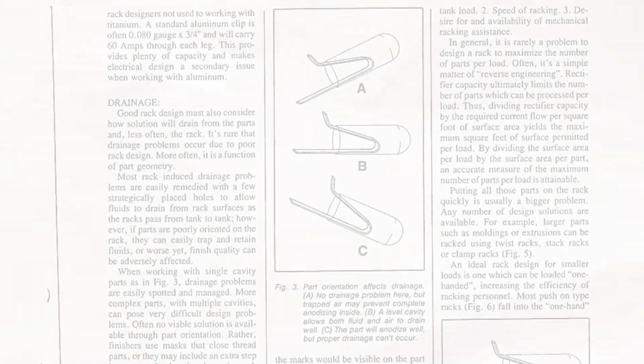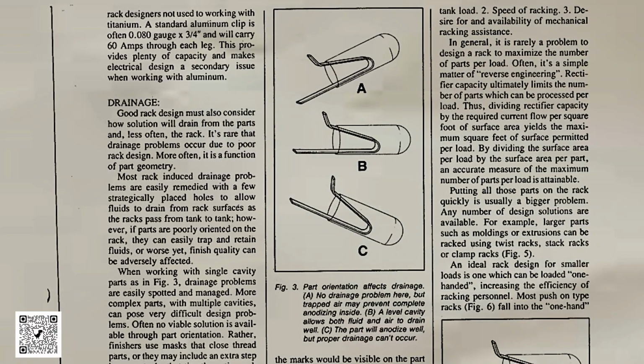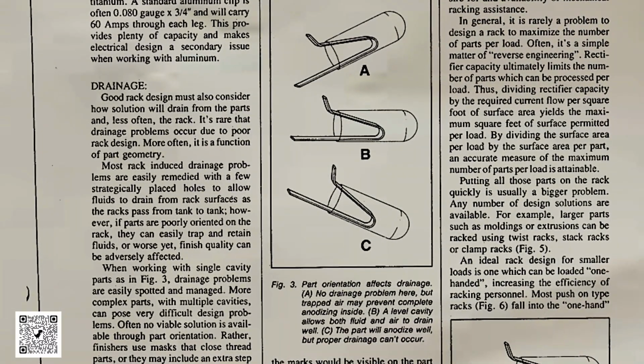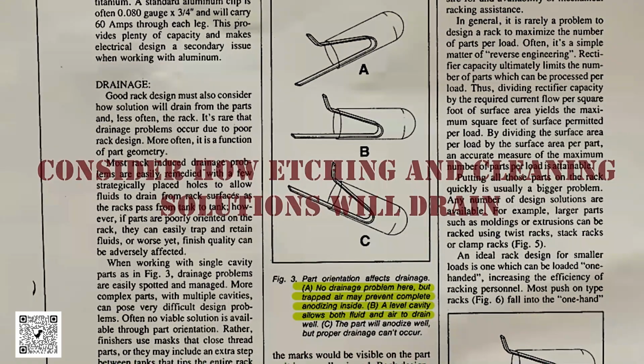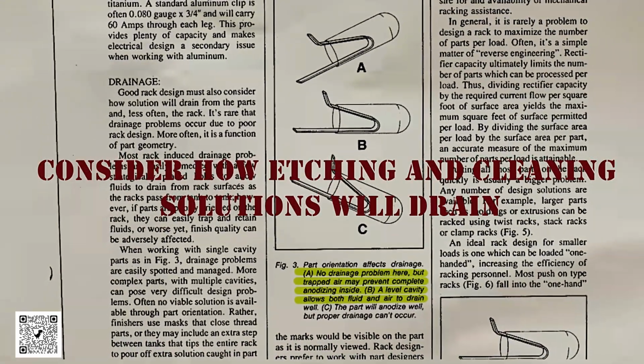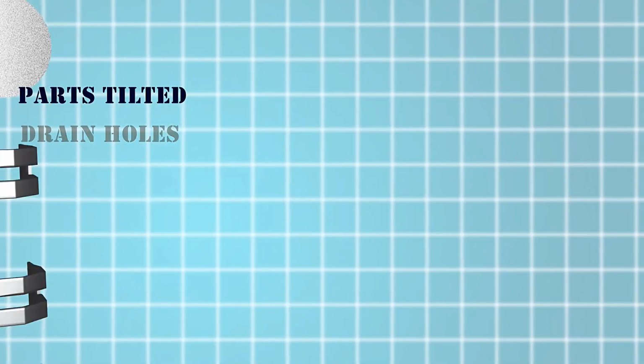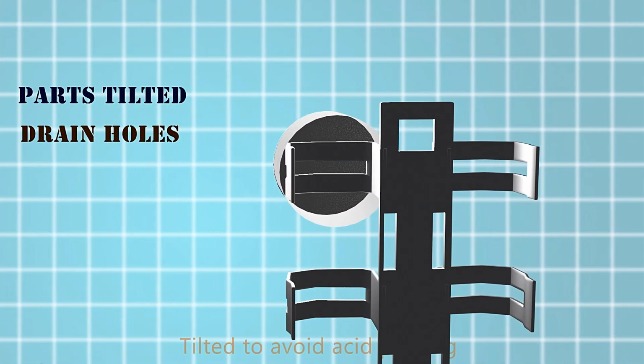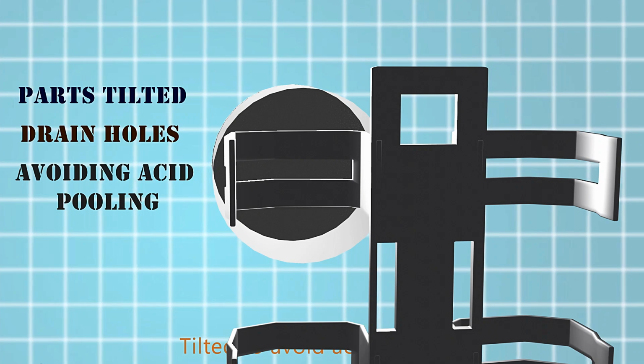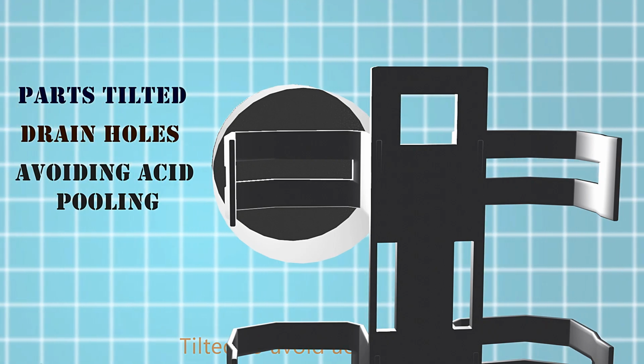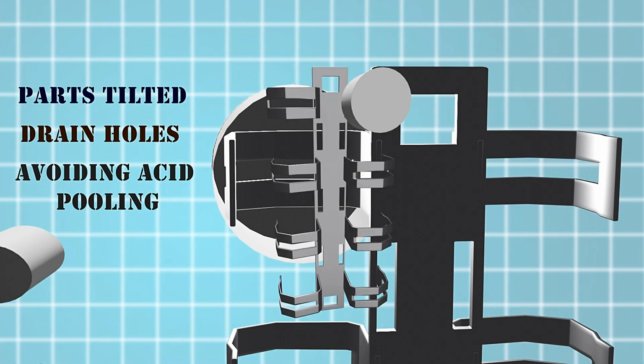Orient parts so that no pockets trap air or solution. A classic rookie mistake is racking a cup-shaped part facing upward. It'll trap an air bubble, and that area won't anodize at all, a perfect little uncoated circle. Instead, angle or flip parts so bubbles escape freely. Also consider how the etching and cleaning solutions will drain. Parts should be tilted or have drain holes at the lowest point to avoid acid or rinse water pooling inside cavities, which can later seep out and stain after sealing.